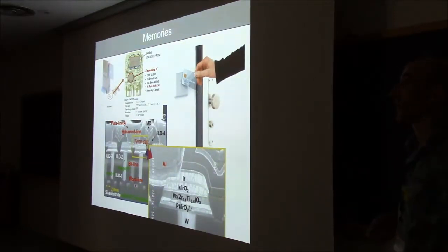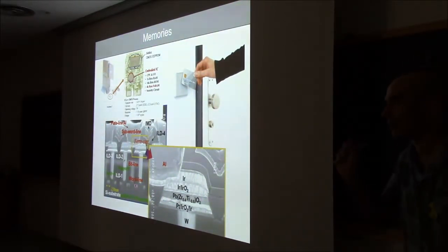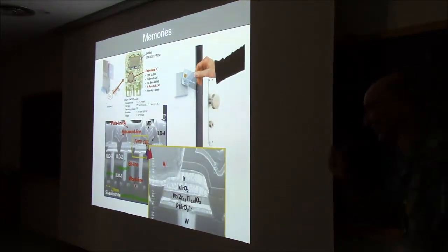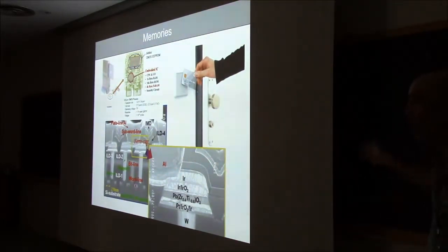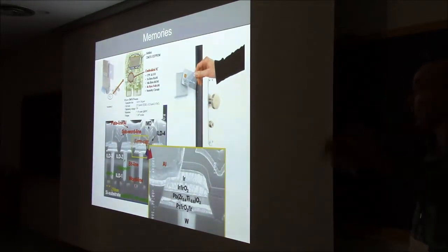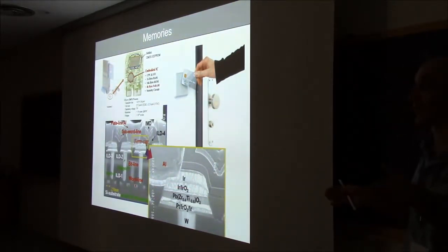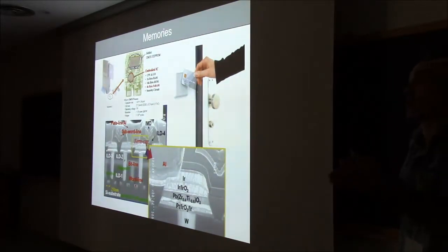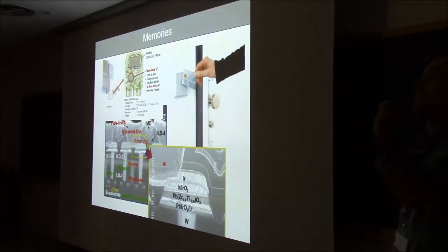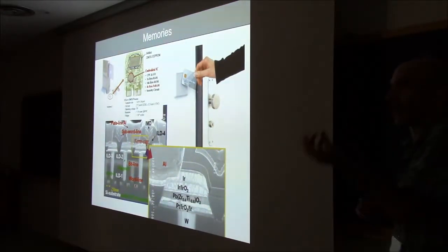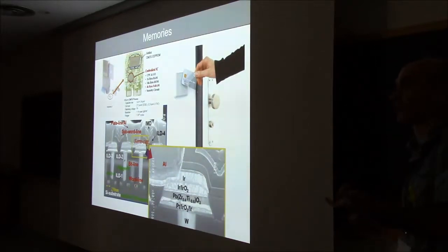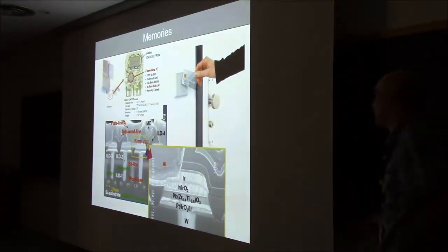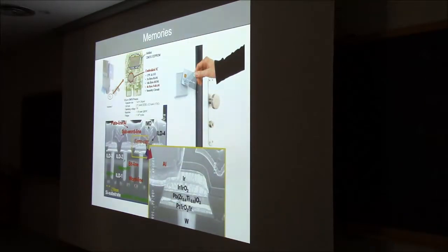With PZT? With PZT, yes. Okay, but it's difficult. There's another problem when you make things smaller, which is that the lateral dimensions also matter, because the lateral dimensions will define how much charge you can collect when you switch the polarization. If you make it too small, even if you switch the polarization, you're not going to get enough charge for you to be able to measure it, basically.